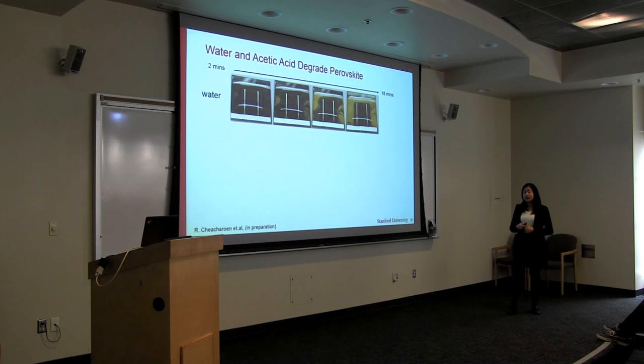The other two things that could cause perovskite cells to degrade are water and the reaction between the encapsulant and the perovskite. So first, as you can see in this picture, this is a perovskite solar cell with water droplets. We can see that it discolored after only 2 minutes and it completely degraded after 18 minutes. So clearly, if you have any moisture or water diffusing into our package, we will see degradation.